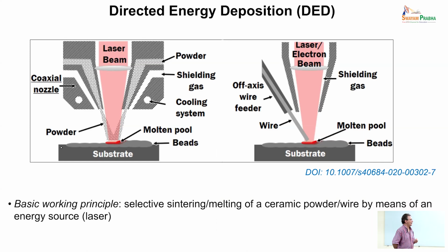So you have a flux of powders through a nozzle, and then you use either a laser beam or an electron beam to locally melt, typically, or simply sinter, but typically melt your powders. And for metals, you can do that in an inert atmosphere in order to avoid oxidation. A variation of the powder approach is to use a wire. So you have a filament of your metal and you melt locally. This is a very nice approach for metals. For ceramics, you still have the issue that you have very fast cooling, and that leads to cracking.